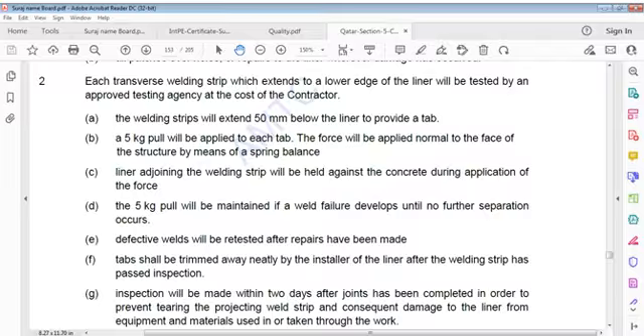Defective welds shall be retested after repairs have been made. Tabs shall be trimmed away neatly by installer of liner after welding strip has passed inspection. Inspection will be made within 2 days after joints have been completed in order to prevent tearing, projection.